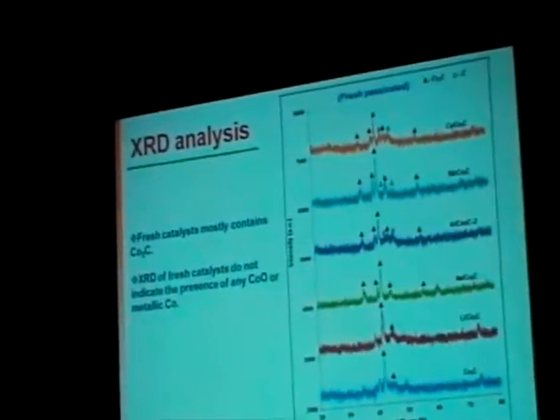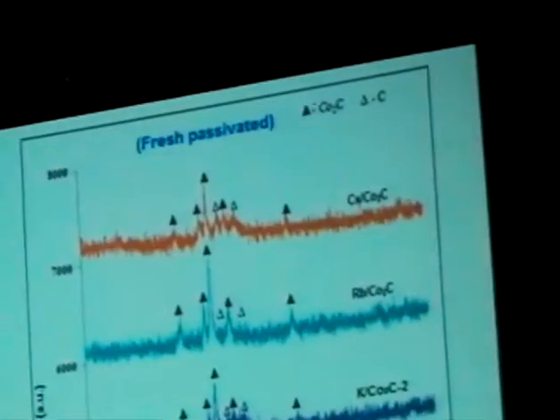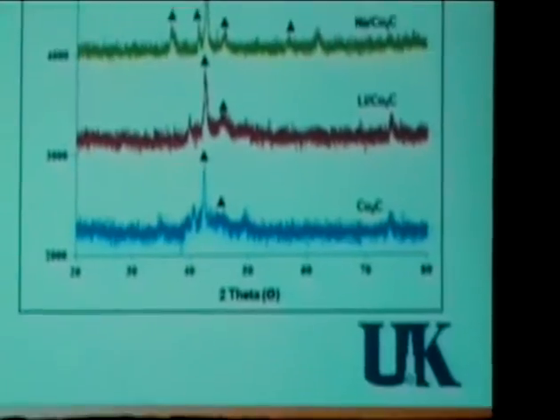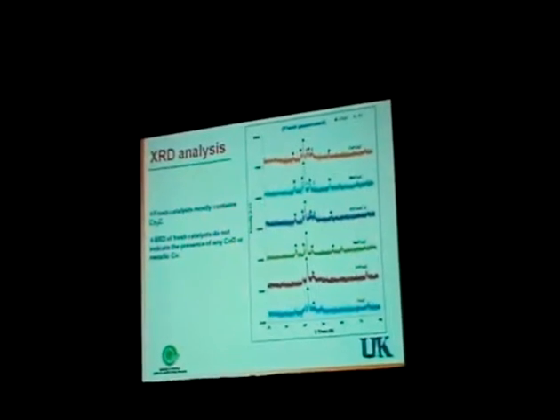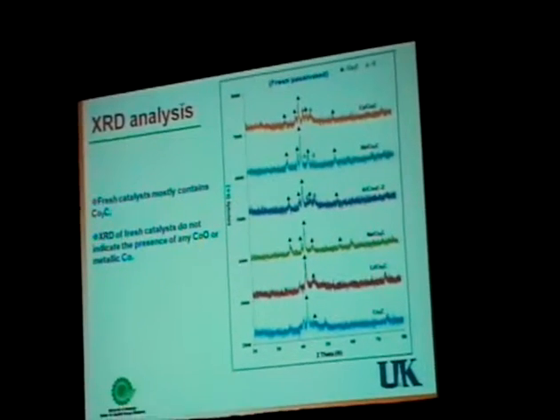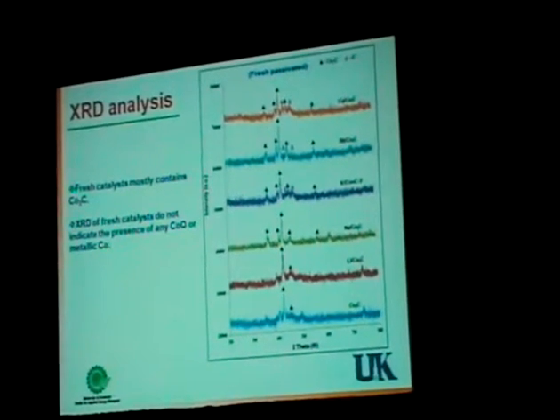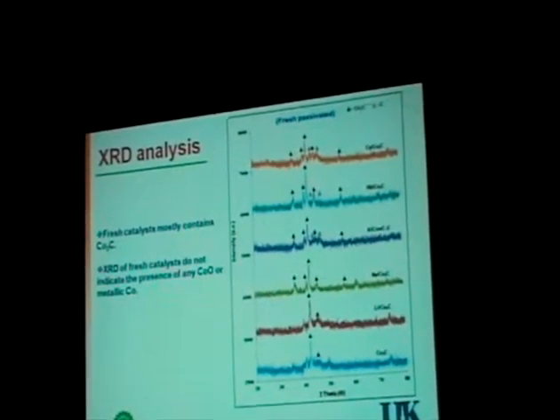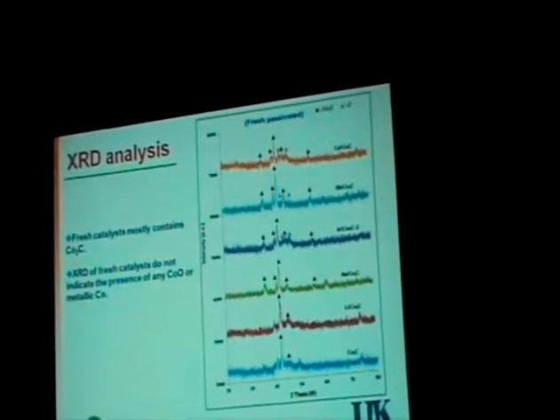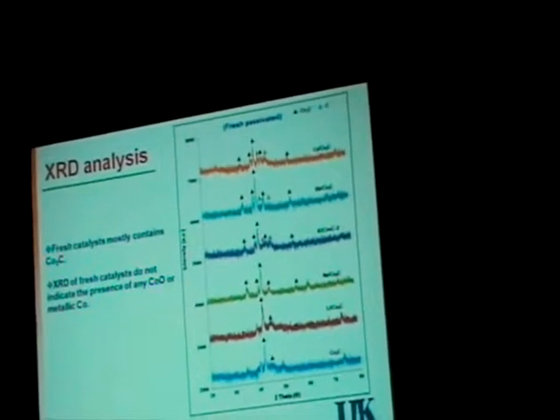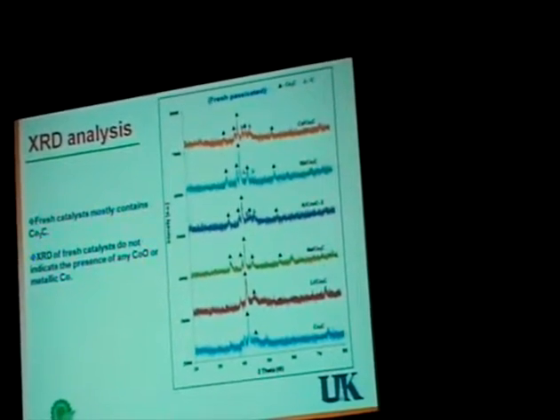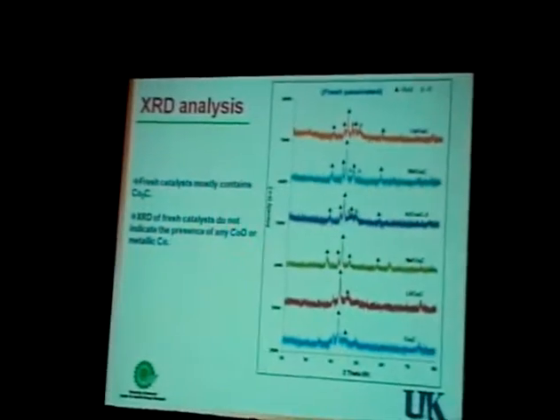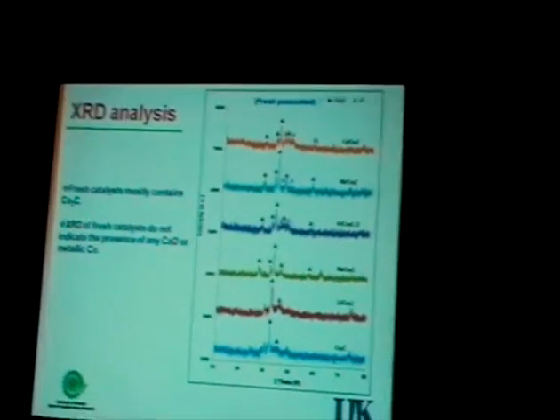The XRD analysis we did on the fresh promoted catalyst, as you can see, shows a dominant peak of the presence of cobalt carbide at 42.5 2 theta. We have additional peaks that indicate the presence of carbon, especially on the cesium, rubidium and potassium promoted catalysts. It means you have an indication of additional carbon that covers the cobalt carbide surface. And we'll see how that affects the water gas shift reaction.